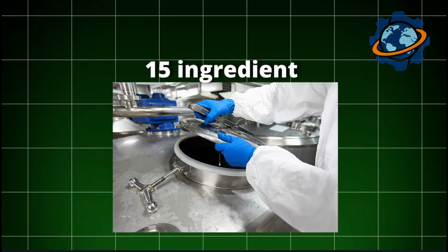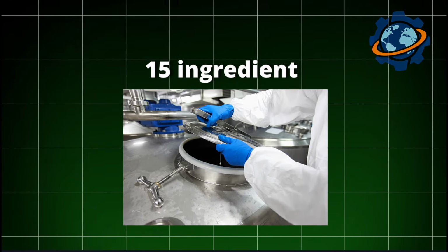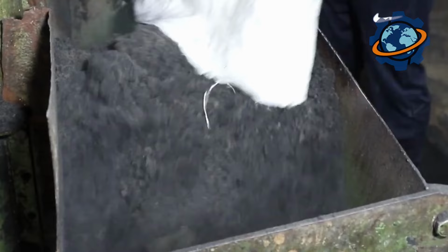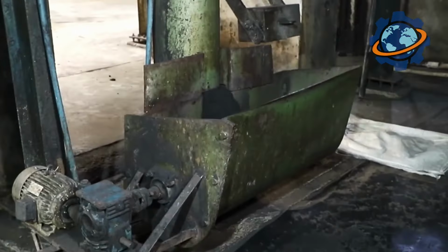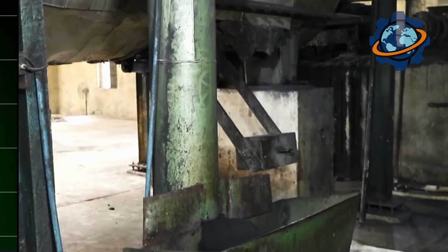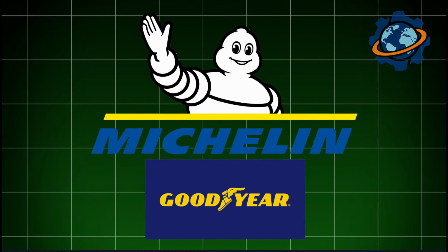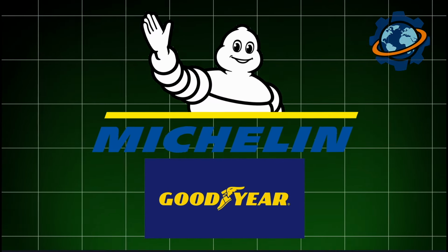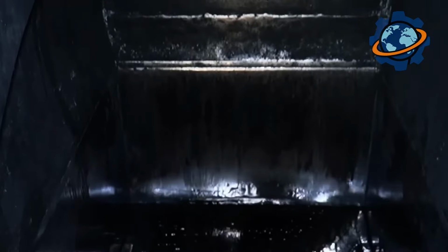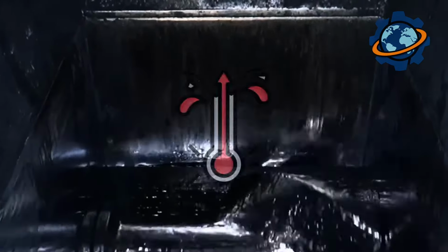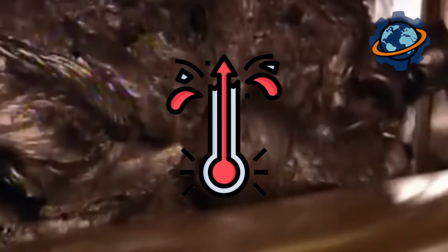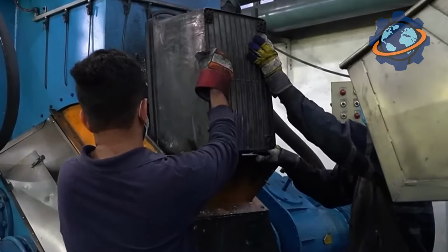Each tire compound contains 15 ingredients mixed in precise ratios. Tread rubber emphasizes durability, sidewall rubber prioritizes flexibility, inner liner uses butyl rubber for air retention. Formulations remain trade secrets; Michelin's compounds differ from Goodyear's, creating performance variations. Mixing takes 12 minutes at temperatures reaching 300 degrees Fahrenheit. The batch, weighing 500 pounds, emerges as uniform black mass ready for shaping.